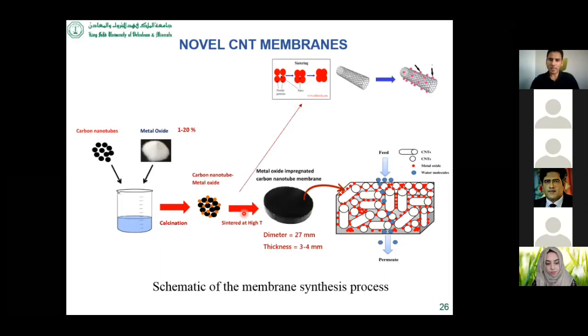So what is basically happening here, at high temperature, the metal oxide particle will be sintered or diffused. So it can be used as a welding agent to hold this carbon nanotube together. So we are not adding any binder, and the entire membrane or composite is made of the carbon nanotube. So here the metal oxide will not only work as a binder to hold tightly these carbon nanotube together, but it will also improve the various feature, especially for water treatment, like the surface area. Even it can modify the surface charge.